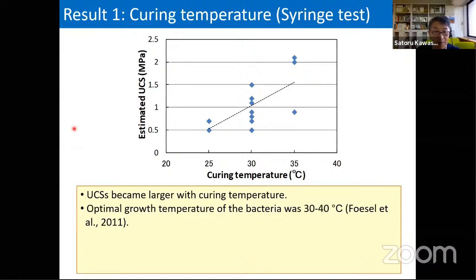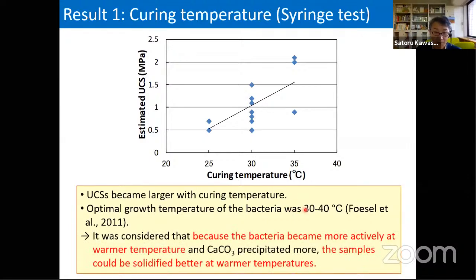This one is a typical result, the curing temperature effect. Curing temperature 25, 30, and 35, and the estimated UCS obtained from the needle penetration test. As you can see, UCS becomes larger with curing temperature. Okay, move to another one.